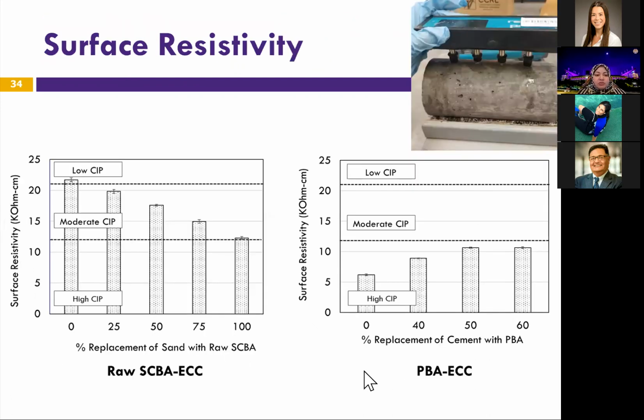We also measured the surface resistivity for both the raw bagasse and the processed bagasse ash. All of the raw bagasse ECC exhibited lower surface resistivity when compared to control and fell in the moderate chloride ion penetration category. For the processed bagasse ash ECC mixture, their resistivity improved when compared to control, but all the mixes were in the high chloride ion penetration category.